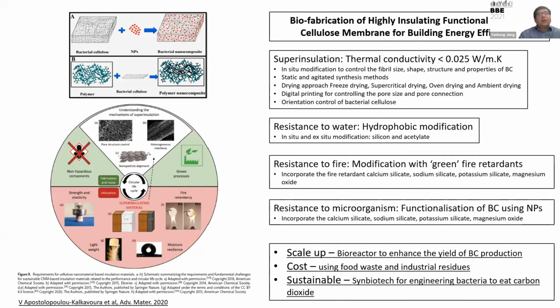In our project, the key technology to be developed is to modify the bacterial cellulose to render it more resistant to biodegradation through an in-situ bioprocess approach. The bacterial cellulose will be in-situ modified with improved functionalities, including hydrophobicity, antimicrobial activity, and fire resistance. Several approaches will be applied, including developing silica bacterial cellulose aerogel, incorporating sodium silicate, or co-culturing bacteria to produce specific nanoparticles in the bacterial cellulose. Due to COVID-19, the project is still at a very early stage, so I don't have too much data to show here. Certainly, we would also like to work on a scale-up process using food waste to reduce the cost.